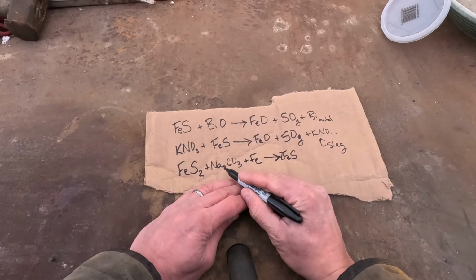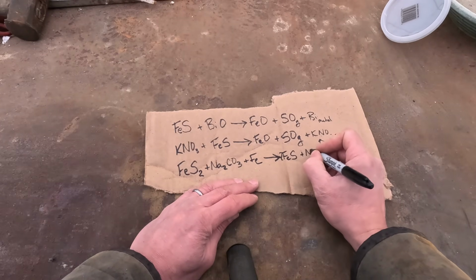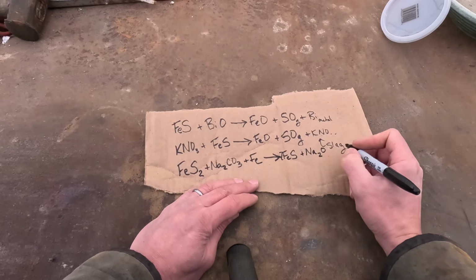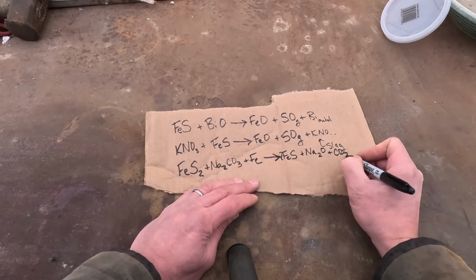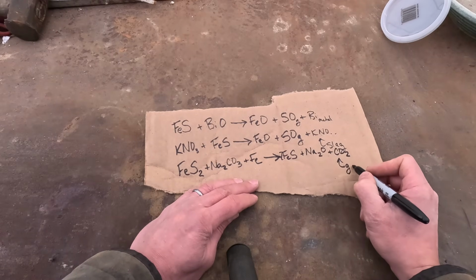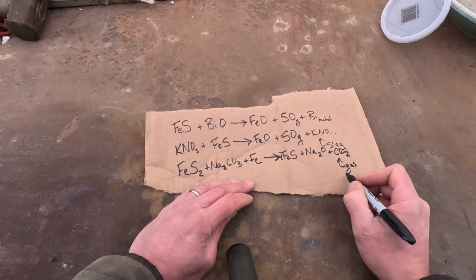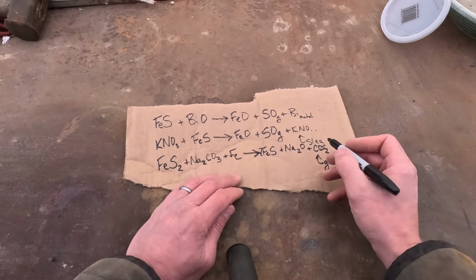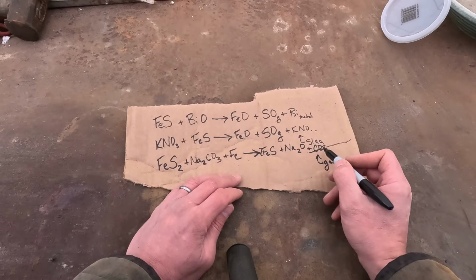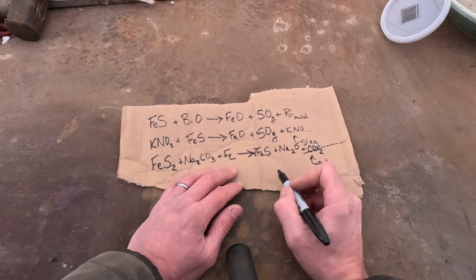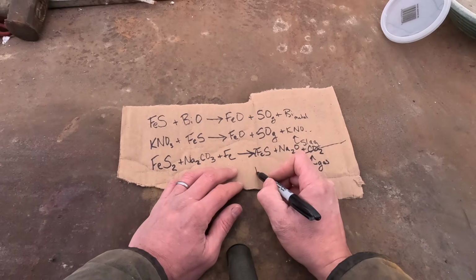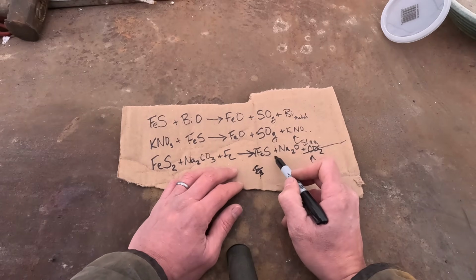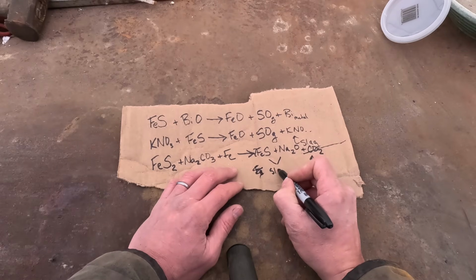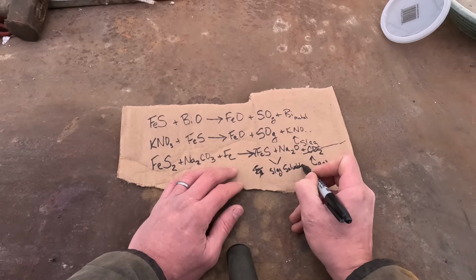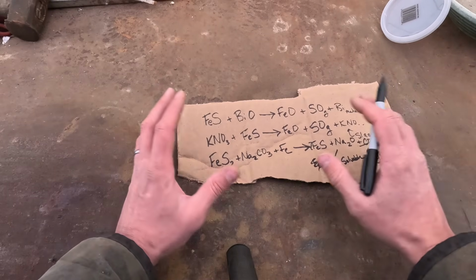And when you heat up soda ash, you end up with sodium oxide plus CO2. This is why this is a gas, and this is why soda ash can froth if you heat it up too quickly, or if the slag is not fluid enough, it will bubble and boil and overflow your crucible as well. So this goes off as a gas, that's out of our crucible. And there's some reaction here, I'm not quite sure what it is, but it probably looks something like this. So I don't know, it doesn't matter, don't worry about it. These two, when they combine, these are slag soluble.